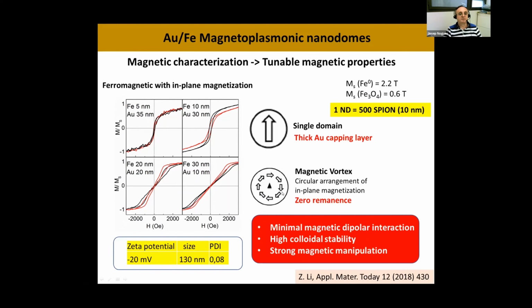This is very important because, as we can see here, this has zero remanence at zero applied field. This means that this system has very weak dipolar interactions, which avoids agglomeration. And this translates into high colloidal stability. And as I said before, it's very easy to manipulate them using magnetic fields. As a simple note, one nanodome is equivalent to 500 superparamagnetic iron oxide nanoparticles. That means that it's much easier to manipulate the nanodomes than the superparamagnetic iron oxide nanoparticles because they have a much higher total magnetization in the system.